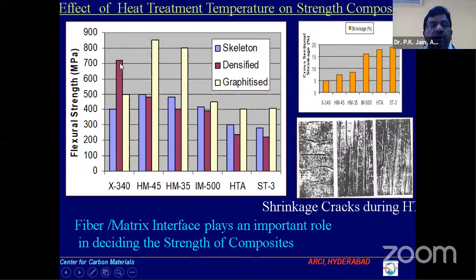It will not reflect directly in the composite properties. If the interface is very strong also, it will not reflect. You require an intermediate interface. It requires a different understanding, because if the material is very strongly bonded, you will develop a crack in the matrix, and these perpendicular cracks will break the composite catastrophically. Whereas if it is intermediate, your crack will propagate along the fiber.